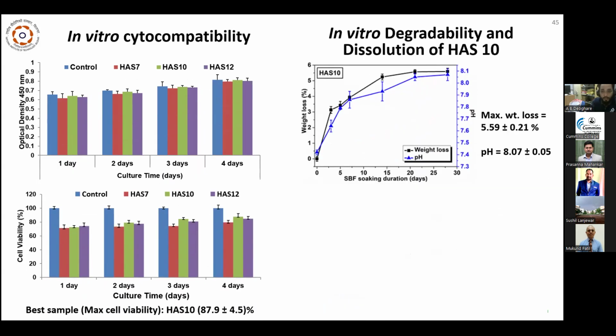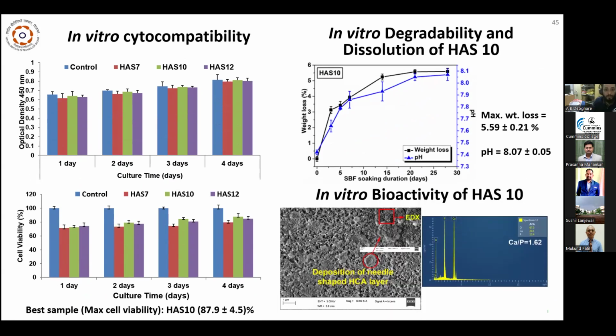Then a cytocompatibility test was also performed, which is basically to show whether the prepared material is non-toxic or not. It is observed that the cell viability is maximum for the HAS10 sample, which is 87.9 ± 4.5%, which shows the material is cytocompatible.